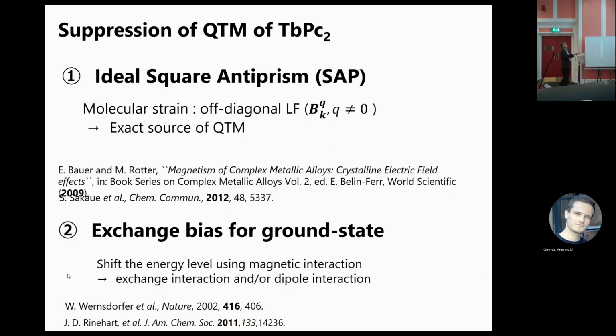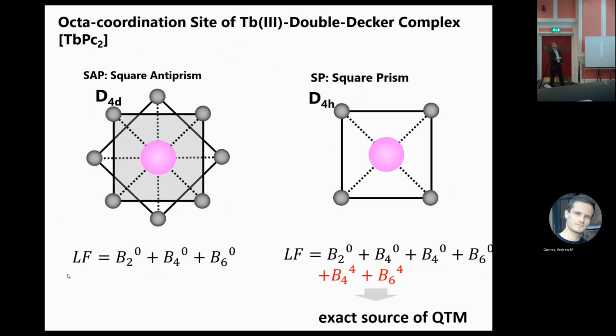So for this purpose, I focus on double-decker compounds to suppress the QTM. For this purpose, ideal square antiprism and exchange bias for the ground state are both very important. For upper phthalocyanine, lower phthalocyanine, no distortion, square prism, D4h. In this case, the ligand field includes B44 and B64. This B44, B64 is the exact source of the quantum tunneling mechanism. But with upper phthalocyanine, lower phthalocyanine, 45-degree distortion, D4d, the ligand field terms B44 and B64 disappear. So the square antiprism suppresses the quantum tunneling.